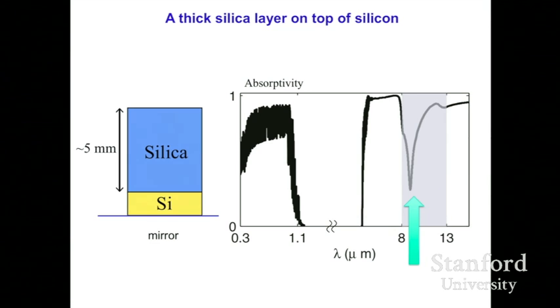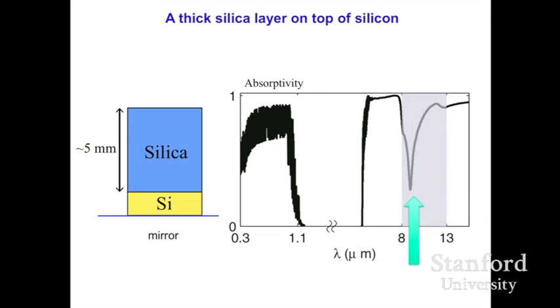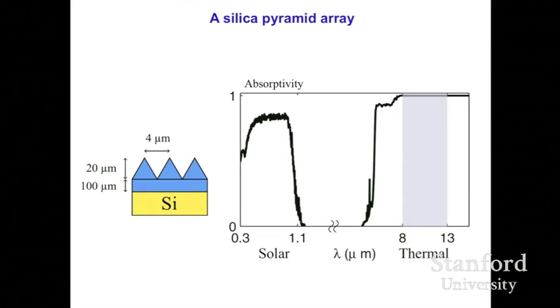But a silica structure like this is actually suboptimum. There is a strong phonon-polariton response of silica, and as a result, there's a large index mismatch between silica and air, and so there's a strong reflection at the silica-air interface, leading to a substantial dip in the 8 to 13 micron window. Instead, what you would like to do is to structure the silica layer.